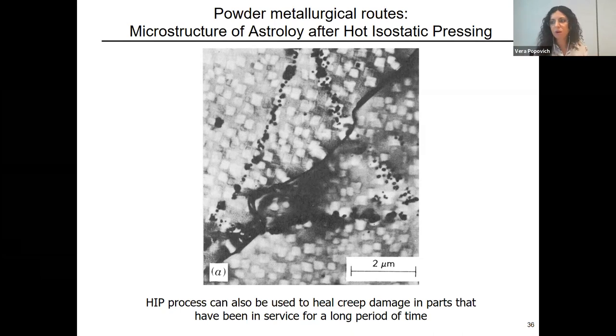On the slide here, you see another application of this powder metallurgical route, so after HIP, you see Astroloy, a nickel-based superalloy, and you have here a cubic shape. Again, remember, it's a cubic shape gamma prime, and you have borides and carbides that are decorating the former powder boundaries.